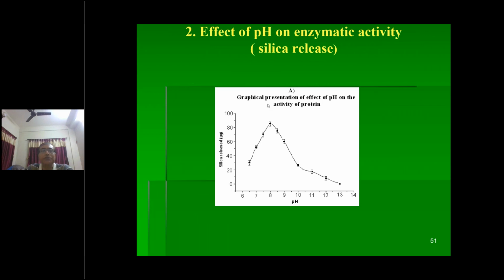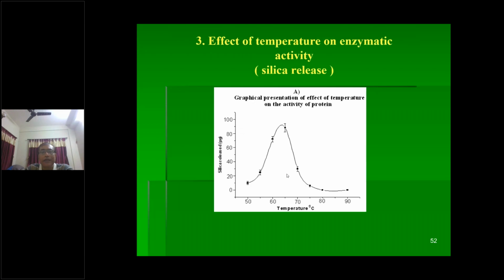Now, these are the characterizations of the enzymatic activity of this protein. We are finding that this protein has its highest silica releasing capacity in the range around pH 8. We have also determined the temperature at which this protein gives the maximum silica release, and it is around 65 degrees.